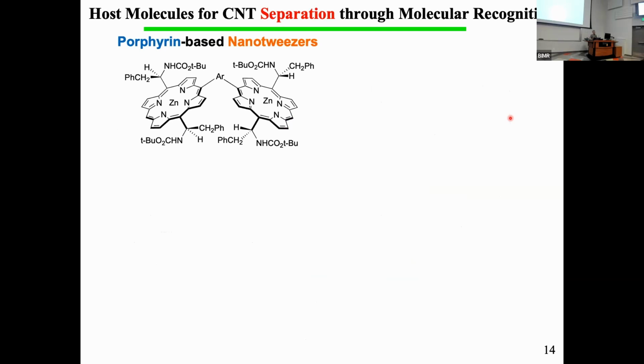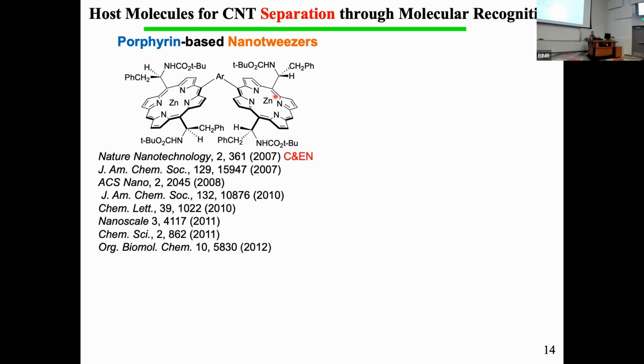Okay, so I will introduce the typical structure of the host molecule from the first generation to the third generation. This is the first generation I've already shown you, the porphyrin-based nanotweezers. And here we put the stereogenic center at the periphery of the porphyrin unit. As I told you, the porphyrin itself has a great affinity towards the surface of the carbon nanotube. And if we put this stereogenic center, this R structure and the S structure can discriminate left-handed and right-handed structures of the carbon nanotube. This is the molecular design behind these stereogenic centers. So these are the publications.